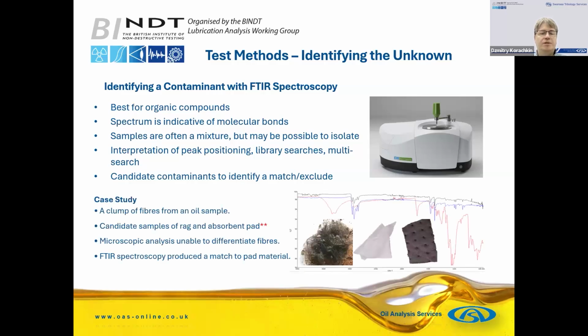So as a case study, we had a customer come in with some fibers that we found in the oil system. They brought us some rags and some spill kit, and we were able to perform analysis and identify that the pad material was a match to the fibers and the other material was not. So they were able to then identify where the contamination is coming from.